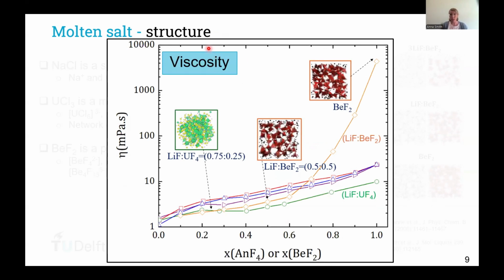If we take viscosity as an example, we see that the viscosity in a mixture of lithium fluoride with uranium tetrafluoride or beryllium fluoride increases as the content of uranium or beryllium fluoride increases. But there is quite a difference between the increase in the lithium uranium fluoride mixture, which is about 1 order of magnitude, versus several orders of magnitude, as you see here, if we add beryllium fluoride to the mixture. So we really want to understand this relationship between the structure of the salt, the thermodynamics, and the thermophysical properties.